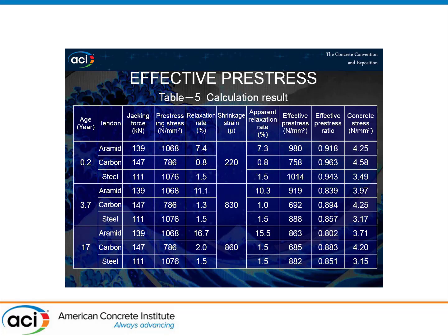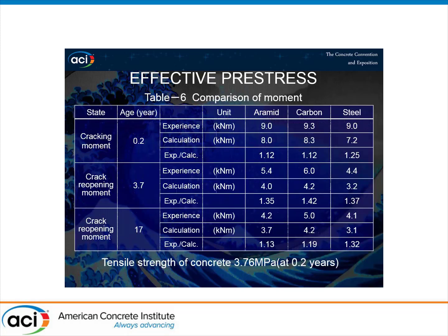This table shows the result of calculation: prestressing stress, concrete shrinkage, apparent relaxation rate, and calculated effective prestress of tendon. The concrete stress by effective prestress was approximately 4 Newton per square millimeter, and cracking moment and crack reopening moment were back calculated using this value and concrete tensile strength measured at the age of 2 months.